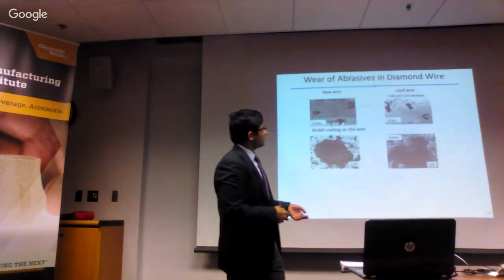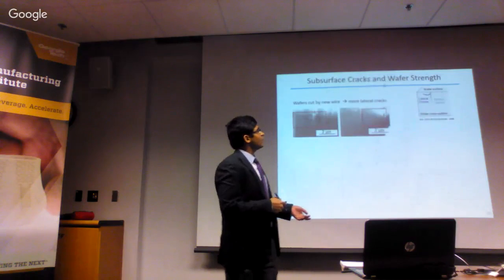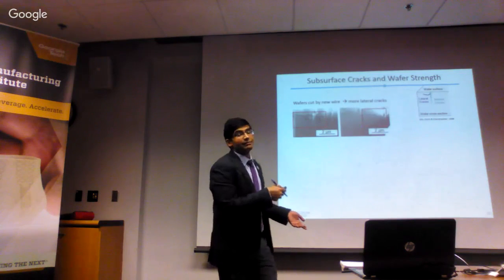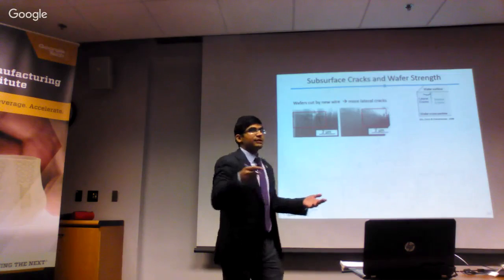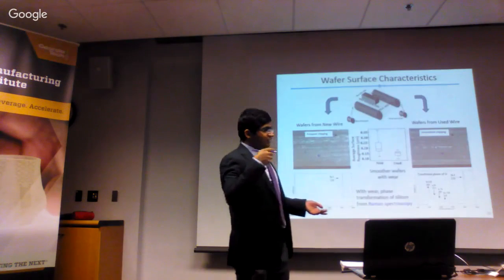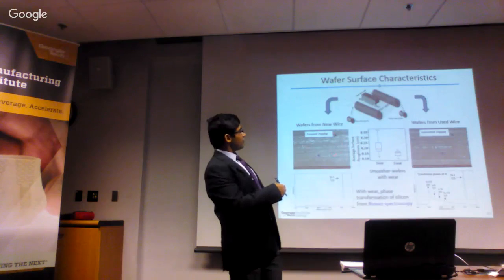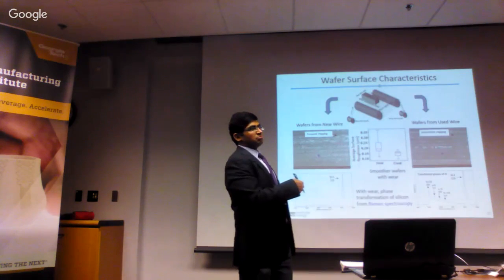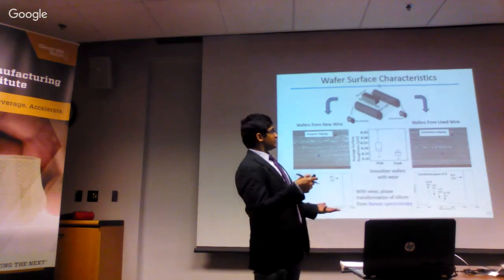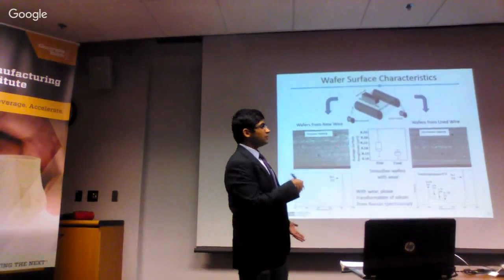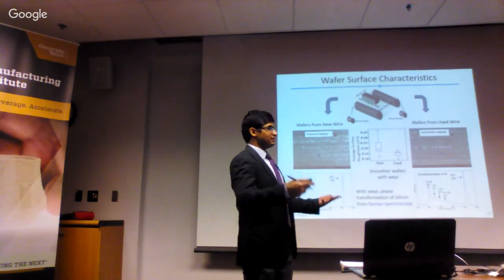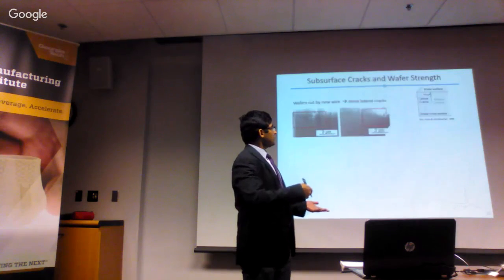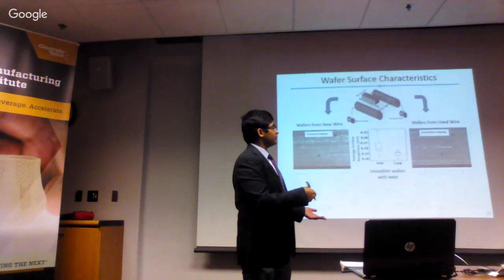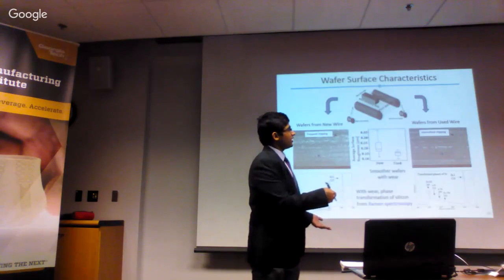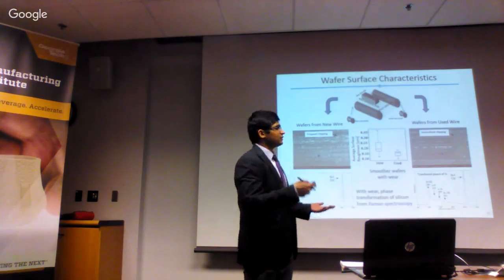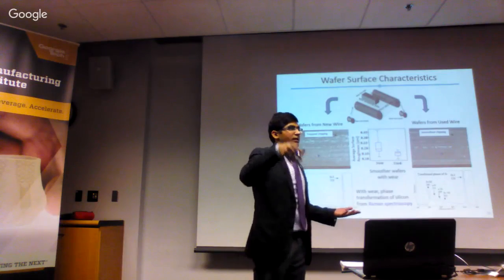In fact, they mentioned that, so you see more lateral cracks on the new wafers, on the wafers cut by the new wire, and they are expected to chip out. And that's exactly the same as what we see on the surface morphology, more chipping. So the results are actually very consistent. The surface shows more chipping, which means there are more lateral cracks chipping out. And that's what we see in the subsurface, whereas the surface for used wire wafers does not show as much chipping because there are cracks which are deeper and median cracks.